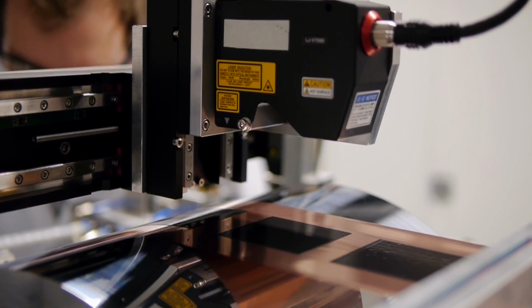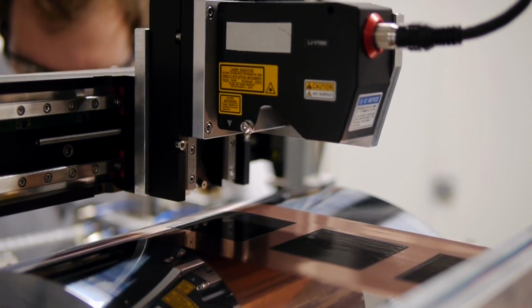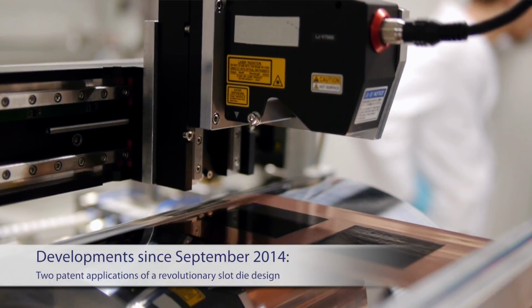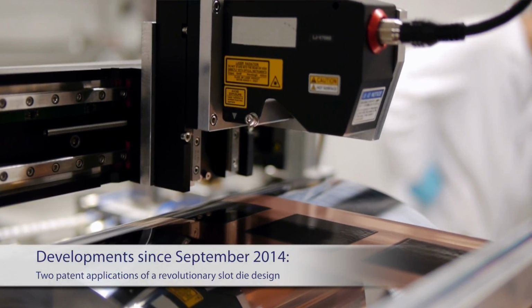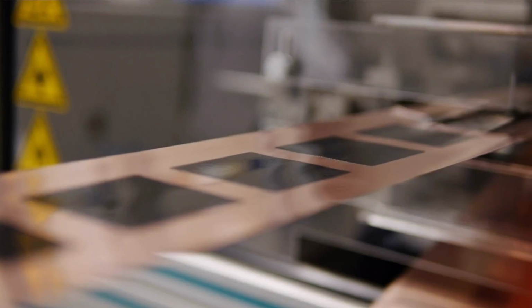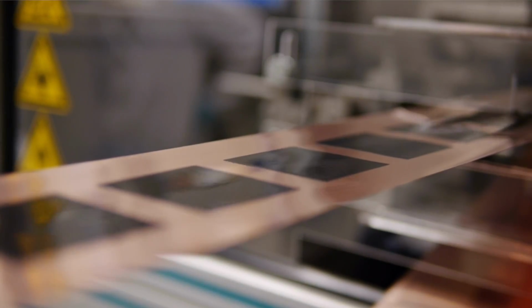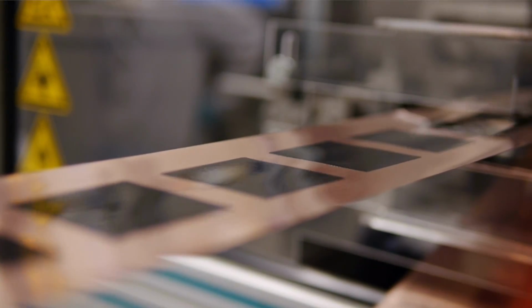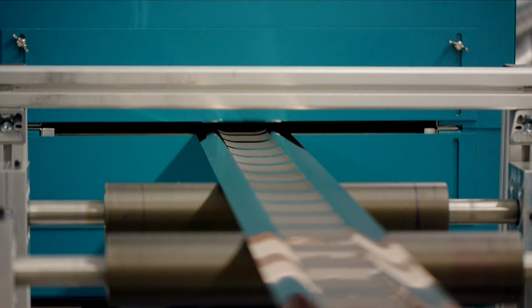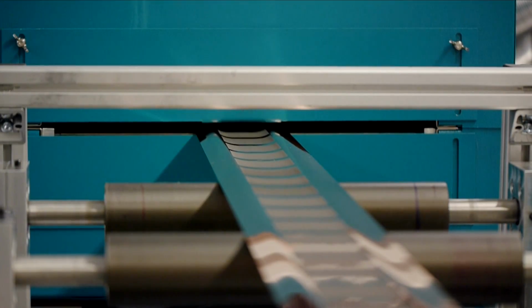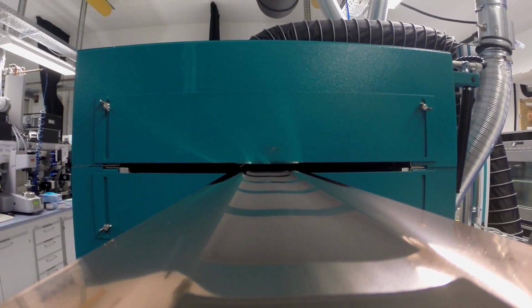So until now we could show that we can coat at 100 meters per minute, which is a limit experts say you don't have to go beyond, because the costs won't decrease that much as your plant costs will increase. For the intermittent coating we developed a technology where we can coat intermittently very properly with defined and sharp edges, and this technology is also capable of really high coating speeds where we can also replace our bypass valve.